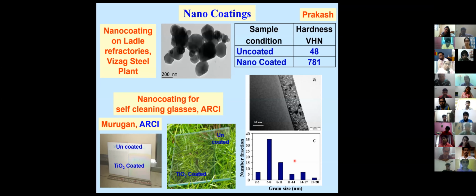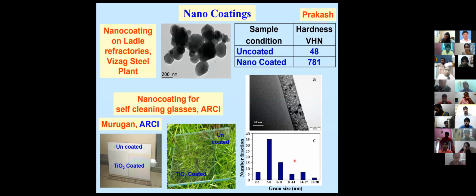Okay, you have a Salem steel plant in Chennai, and there is a JSW Jindal steel plant, and so on and so forth. All these steel plants have large containers called ladles, which are nothing but a container made up of refractory bricks, like the bricks in your home walls. When you take liquid metal at 1600 degrees centigrade, and this ladle holds the liquid metal, there is a lot of wear and tear. People have found this to be a big problem, and very frequently you have to change the refractory bricks.